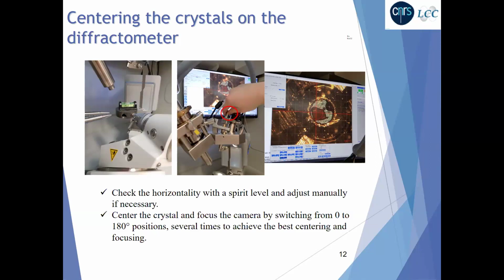We will now have a look at how we can center the crystals on the Synergy. So in the first step, we will check the horizontality with a spirit level, as you can see here, and we can adjust it manually if necessary. Then we can start the centering of the crystal and focus of the camera by switching the position of the cell between 0 and 180 position, several times to achieve the best centering and focusing, as you can see here.